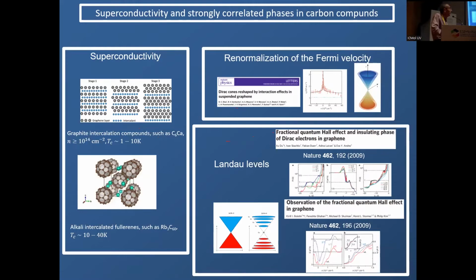And there are some, especially the so-called graphite intercalation compounds. It was known that they were superconducting up to 10 kelvins or so way back. These are basically heavily doped graphene planes because they are surrounded by metals, alkaline metals or calcium. And these metals donate a lot of electrons to the graphene layers. And then when you apply a strong magnetic field, you also see signs of some kind of magnetism and things like that. And there is the issue that the Fermi velocity of graphene changes a lot because of interactions if you probe it in well-designed and very clean samples.